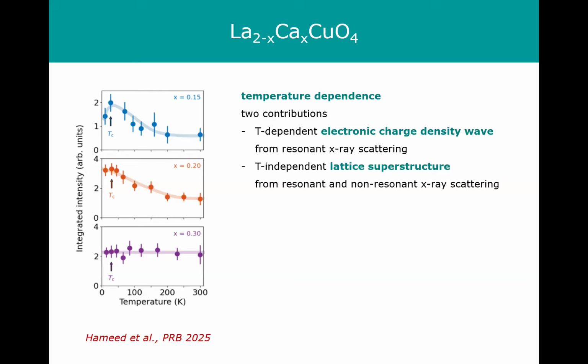Okay, so now when you increase the doping level, this temperature dependence gradually goes away, and at the highest doping levels, 30% upwards, the superstructure intensity is more or less temperature independent. And that indicates that it is not actually charge order, which is expected to go away at some reasonable temperature, but rather this is some kind of lattice superstructure.